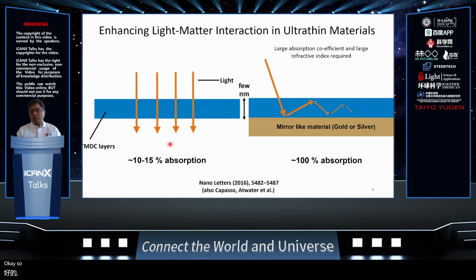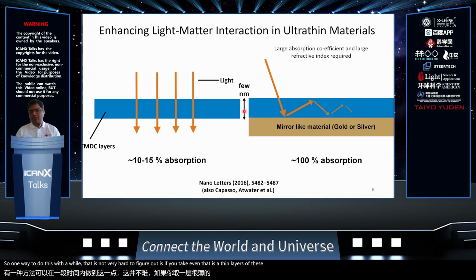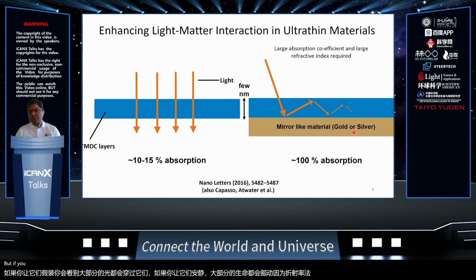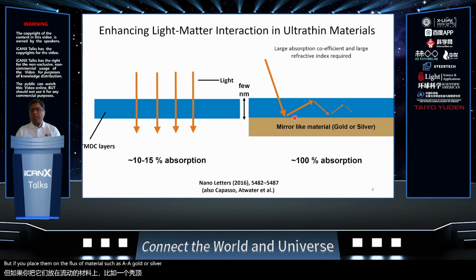Okay, so keeping all these interesting and exciting optical properties in mind, our goal was to see how we can trap light in these materials very effectively. And certainly you can use high-Q optical cavities, but the fact that the optical constants of these materials themselves are so high, we took the approach of trapping light, or self-trapping light, within them. One way to do this, which was actually not very hard to figure out, is if you take even very thin layers of these materials and have them freestanding, most of the light will go through them. If you make them quite thick, most of the light will get reflected because of the refractive index mismatch. But if you place them on reflective materials such as gold or silver, you will have propagation losses, large propagation losses, as light goes through it.